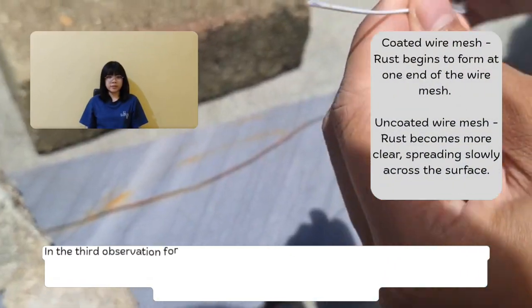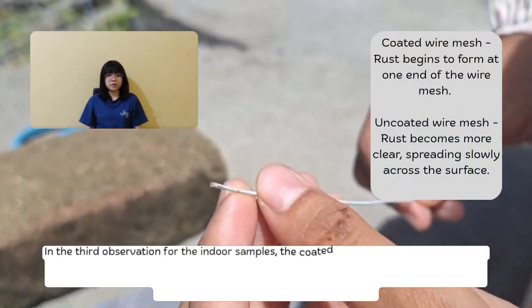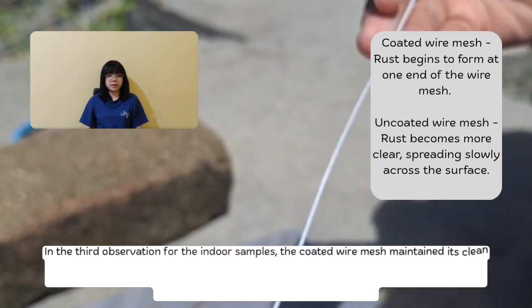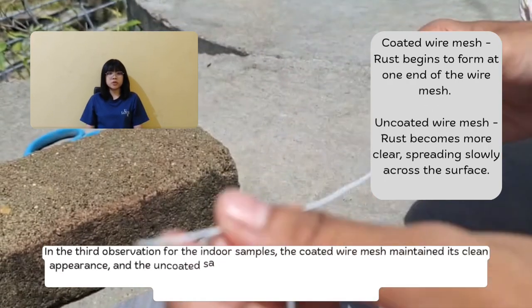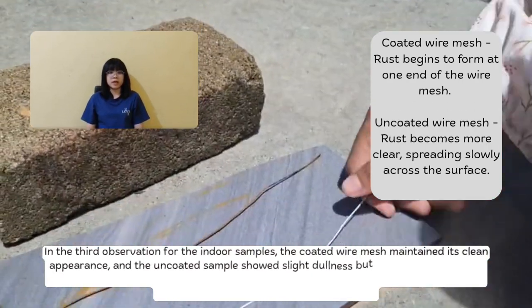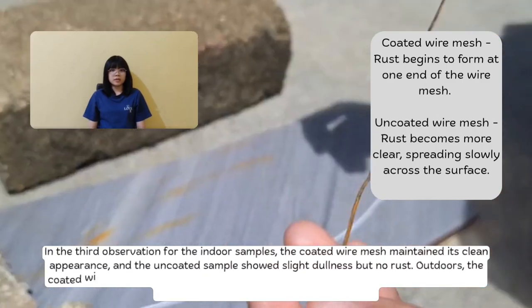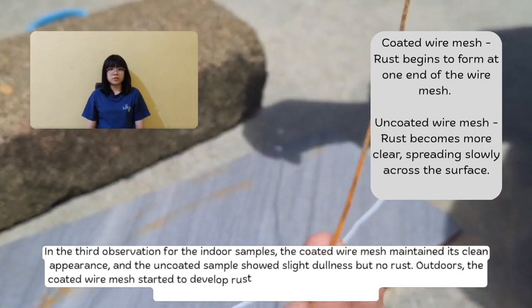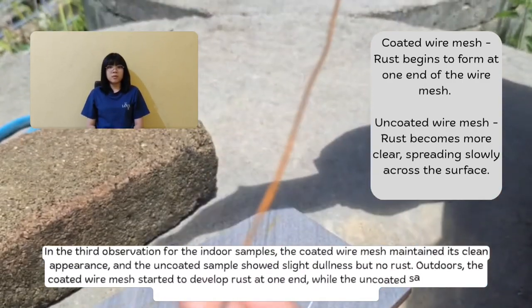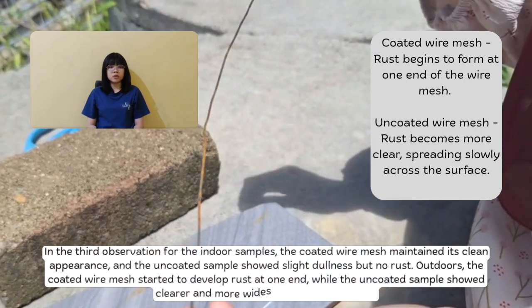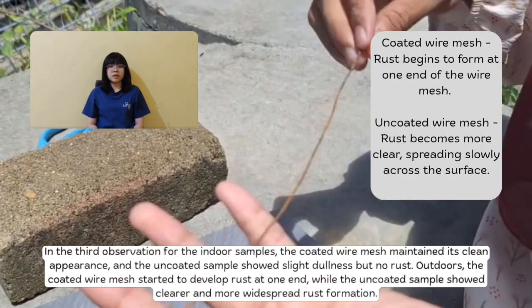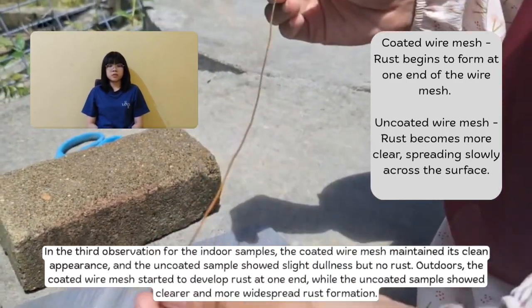For the indoor samples, the coated wire mesh maintains its clean appearance and the uncoated sample shows slight dullness and no rust. In the outdoor, the coated sample starts to rust at one end, while the uncoated sample shows clearer and more widespread rust formation.